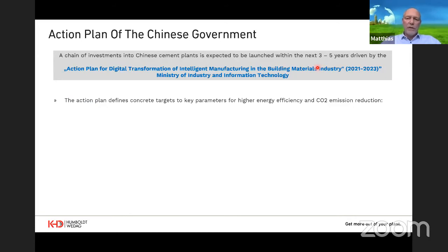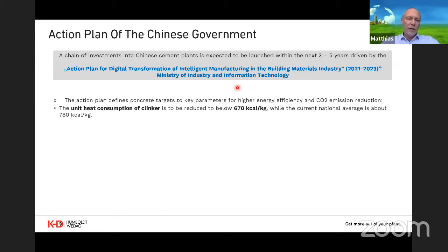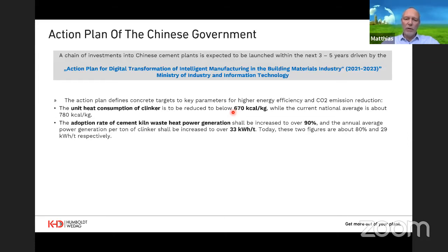If we switch over to China specifically, we see that there is a direct plan of the Chinese government that is being put in place, and that has massive investment and modernization implications for this Chinese cement industry. There's a plan for digital transformation of intelligent manufacturing in the building materials industry, and the requirements formulated here are very precise. This action plan defines concrete targets for key parameters for higher energy efficiency and CO2 emissions reduction. First of all, there will be a benchmark to be reached in terms of heat consumption per kilogram clinker that is considerably low at 670 kilocalories per kilogram.